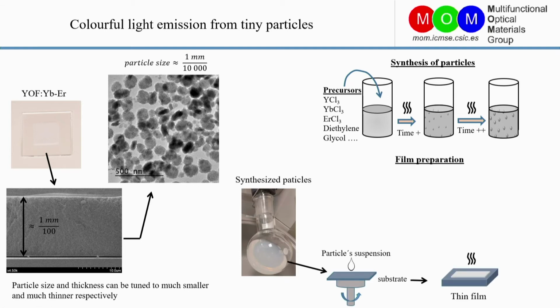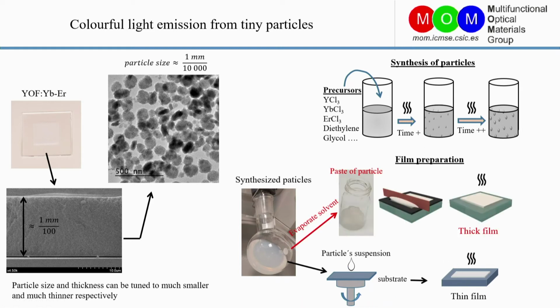We can directly use this particle suspension to prepare thin films. We drop some suspension on the substrate and spin it to have the thin films. We also heat these samples to crystallize the particles. In order to have thick films, we prepare a paste of particles by evaporating the solvents of the particle suspensions. Then we pour the paste on a substrate and spread it on the surface to have the coatings. We also heat the samples to crystallize the particles.